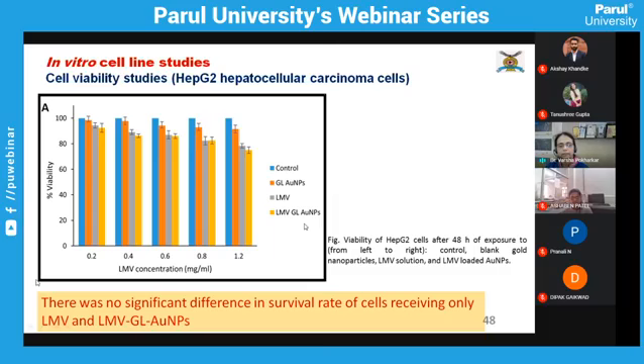So what we have observed is that by changing the concentration of lamivudine, there was no significant difference in the survival rate of the cells which received only lamivudine or the lamivudine capped glycyrrhizin. So this indicates that they are quite biocompatible.